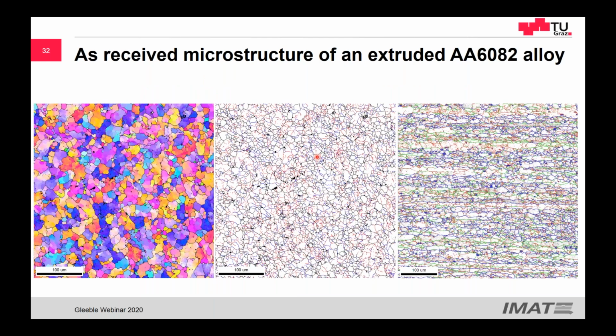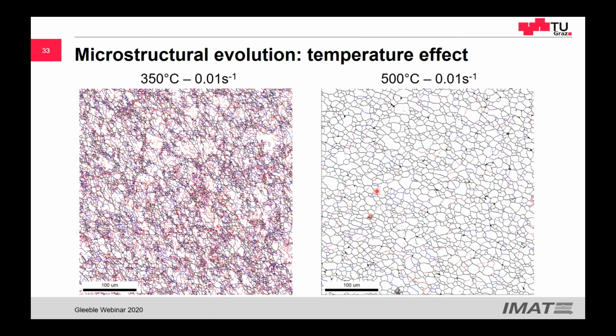Okay, so let's come back. We started with this microstructure, we go to 500 degrees, and we increase the microstructure a bit. So we didn't refine the grains, and this was very interesting. What is the meaning of this? The meaning of this is that we will get refinement of the grains only at the correct conditions. That means only at the conditions where we produce a substructure that is smaller than the one that we get at the beginning. And this is, as before in the compression tests, dependent on temperature and strain rate.